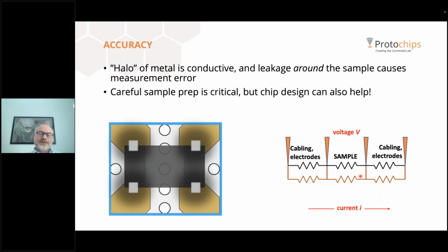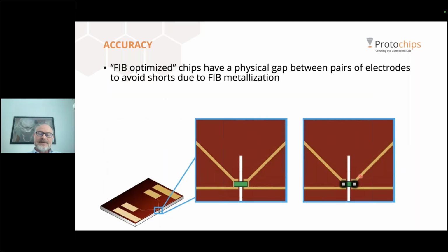But one interesting solution comes down to chip design. As I mentioned earlier, we offer electrical E-chips without a membrane. So there's a physical gap between pairs of electrodes, and deposited metal can't span across that gap. The notch is long enough so that it extends beyond a halo completely. And this is a real advantage for FIB users since you can mount, form contacts, thin in place, and image at high resolution. Another solution lies with avoiding FIB metal altogether.